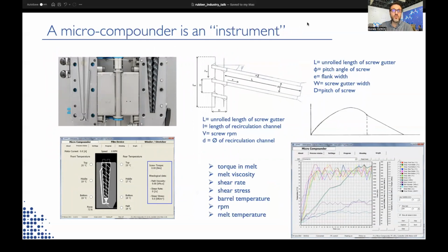In Explore Microcompounder, while you are processing your material, it's also possible to retrieve inline rheological data, such as viscosity, the shear rate, mechanical energy input, die pressure. This is possible since we have a dedicated rheological model of the compounder which provides us to generate these data. By using this option, researchers can track the changes of the molecular structure of their material in situ. If we particularly focus on the rubber compounding, you can follow the mastication process, for example, or you can follow any possible marching or scorching in your compound. We believe that it's a very useful tool for rubber compound development.